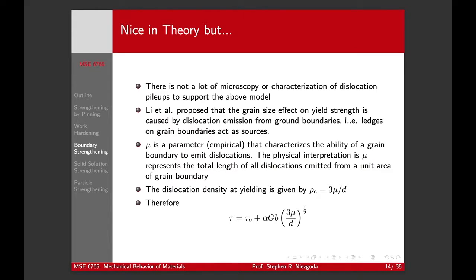The truth is, grain boundaries are really complicated structures. Some grain boundaries are really good at acting as sinks for dislocations. They'll just suck dislocations up. The dislocation will run right into the grain boundary with no resistance and boop, out of existence. Other grain boundaries are basically impenetrable walls and the dislocation just bounces right off. Other grain boundaries can act as sources, and they can emit dislocations into the other grain. And the rate at which they will emit dislocations into other grains can be strongly dependent on the stress that is there.